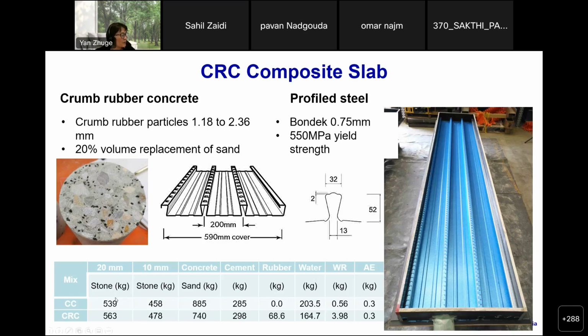So these are 2 groups of testing we did. We have 2 different sizes of coarse aggregate, 10 and 20 mm, concrete, cement, rubber, water, and other materials. So CC is normal concrete, and CRC is crumb rubber concrete. For crumb rubber concrete, we have 20% rubber replacing the sand.